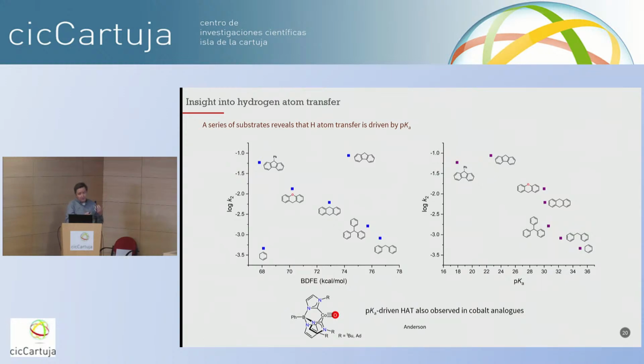So we looked also at a series of substrates for understanding something about this hydrogen atom transfer reaction. So this is a sort of standard set of substrates here. So we can plot the relative rate of reaction for the hydrogen atom transfer reaction versus, for example, the bond energy for the CH bond that's been abstracted. So for example, for triphenylmethane, it's a CH bond that's around 75 kcals per mole. And you see there's not really much of a correlation.